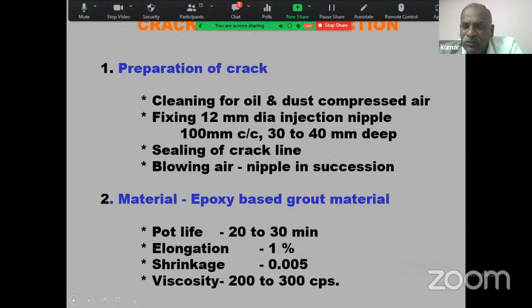Then fixing of 12 mm dia injection nipple. That is the 12 mm or 10 mm or 14 mm, whatever it may be. The selection of the nipple size depends upon the depth of the crack. Based on that, you can fix your nipples, seal the crack line, and blow air in succession from nipple to nipple and remove all the dust which is available there.